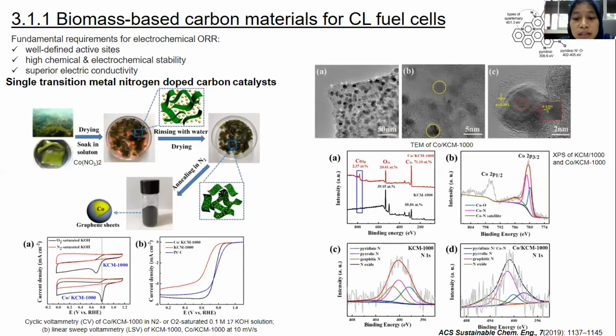And biomass-derived transition metal nitrogen-doped carbon materials have been considered to be promising ORR catalysts. In this paper, they obtained heteroatom-doped carbon, Co-KCM, by directly carbonizing kelp pre-impregnated with cobalt. We can see from the TEM that cobalt nanoparticles are uniformly dispersed in the sample. With higher magnification, we can see that the surface of the cobalt nanoparticles was encapsulated by multilayer graphene. During annealing at high temperature, cobalt acts as a catalyst to facilitate the graphitization of carbon around them and form this core-shell structure. XPS data reveal the presence of Co and CoO.